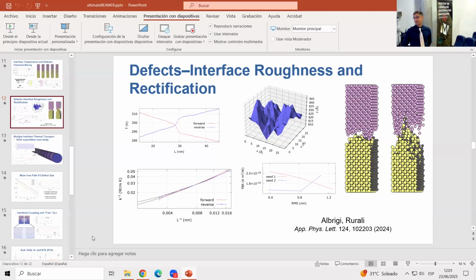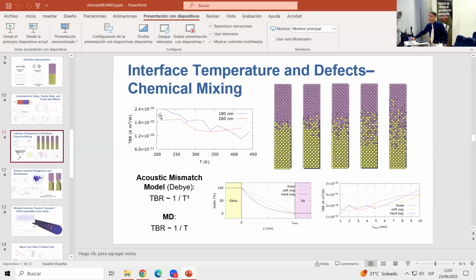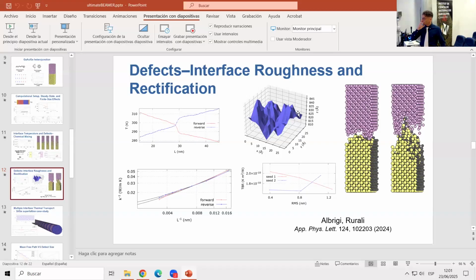Yeah, I have to mention that here I performed this simulation where the interface temperature was kept at 300 Kelvin. So probably in a real device, you would have some heating, it would heat up a bit, but I have shown a few slides before how temperature affects our simulation, the contribution of thermal boundary resistance. So I would say these results are okay. We are actually simulating conditions that can be found in real-life applications and technologies according to the interface temperature. But I have to mention that the thermal gradients that we deal with in this simulation are completely not realistic.